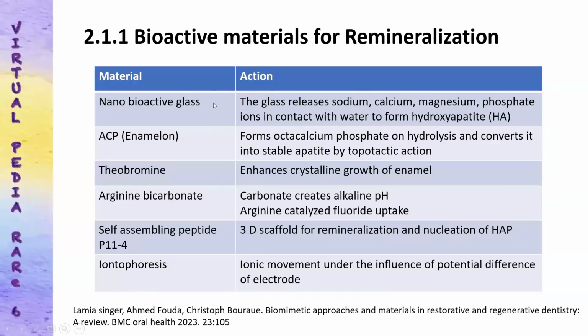These are the materials which can help us to form the repairing of the decalcified enamel or dentine. So nano bioactive glass, enamelon, theobromine leads to formation of hydroxyapatite crystal. Arginine and bicarbonate has got a unique purpose. Arginine catalyzes the fluoride for uptake and carbonate creates an alkaline environment. So this helps us to form the fluorapatite crystals, which is resistant to demineralization as compared to hydroxyapatite crystals.